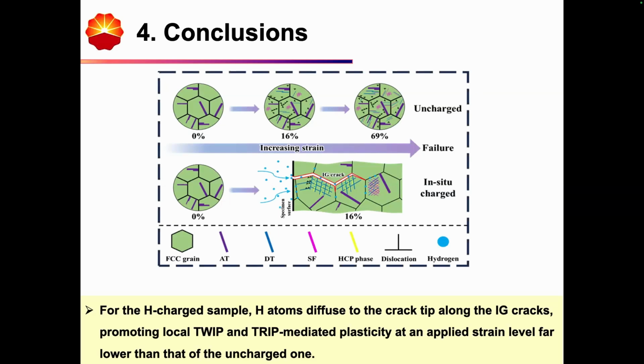For the in situ charging, during charging it has formed some secondary cracks, and these secondary cracks promote some new phase with low surface energies, and hydrogen can transport from this new surface.